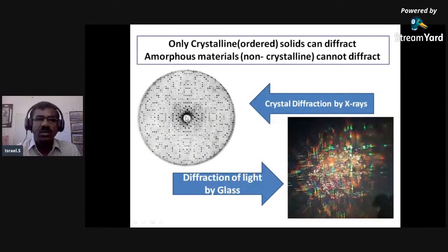First and foremost, if it is a good crystal, then you get a diffraction pattern. If it is a bad crystal, like a glass, which is not a crystal at all, which is amorphous, then you don't get any diffraction. It's not possible to get X-ray diffraction. You won't get any X-ray diffraction or anything. So the moment you get a good diffraction pattern, then you can say the crystal is actually very good.